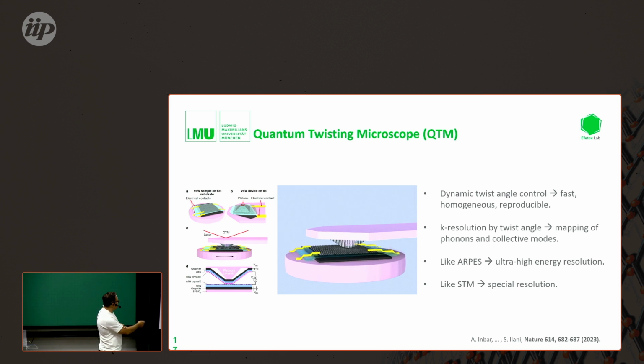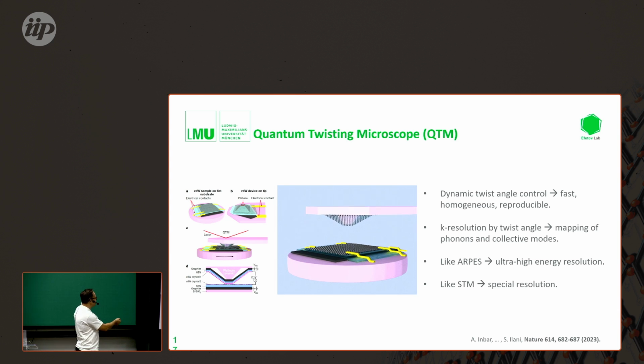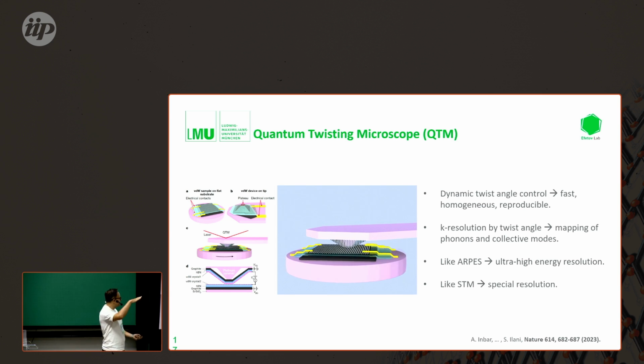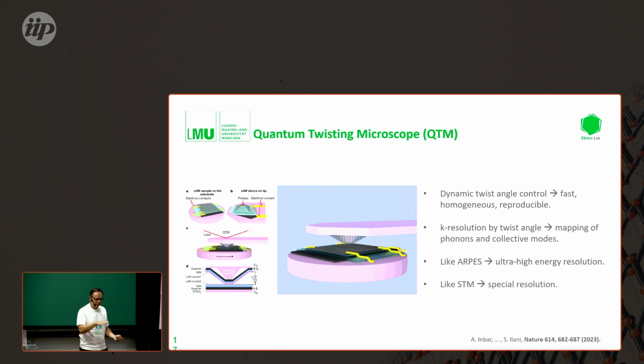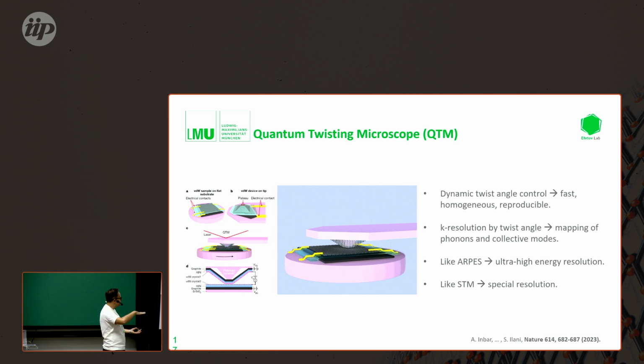And the idea of this technique is the following. Instead of just collimating 2 sheets of 2D materials at the same time, the idea is to separate them, to put one of the layers on this tip, the other layer on a substrate, and make the substrate rotatable. What you can do is combine those materials in different locations. You can change the twist angle. You can also find with this tip an unstrained region of the device. You can repeat these measurements many times.